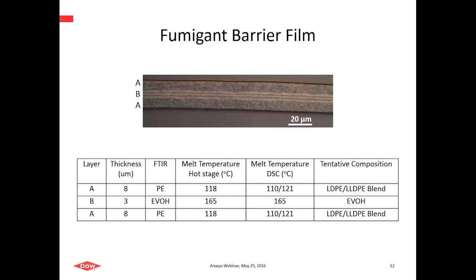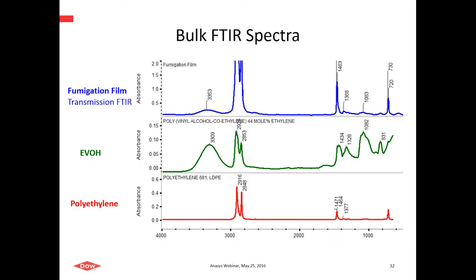We try and understand composition also based on melting behavior using optical hot stage microscopy or DSC, and that can be used to make assignments of layer compositions. And in this example, the conclusion was that this was a three-layer film with an ABA structure, a central core consisting of EVOH, and then two flanking layers that were blends of two different types of polyethylene. So we took a thin section of this in cross-section.